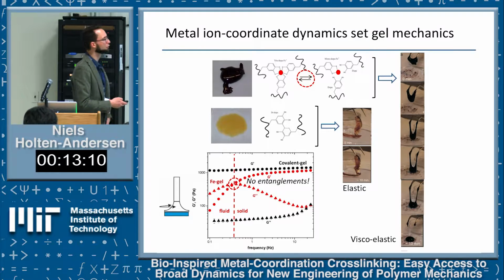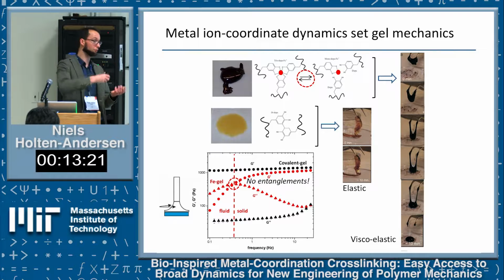The types of techniques we use mechanically to really try to understand the mechanical properties of these viscoelastic materials is called rheology. Without going into too much detail, what you can do with these rheological measurements is take your material, put it in a rheometer, and oscillate the gel at a range of frequencies. If you do low frequencies, that means you're deforming the material very slowly. If you do high frequencies, you're deforming the material very fast.